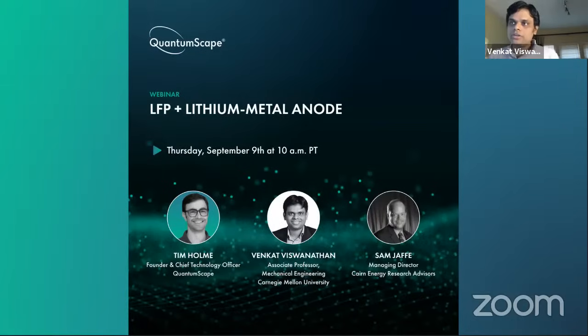One important point to note here is that lithium metal can come in two flavors. The flavor that we've discussed here is the anode-free configuration, in which the lithium metal is plated on the first cycle. The second configuration, also being pursued widely, is to have a preformed lithium foil on the current collector, copper, and use that lithium foil in a lithium metal LFP battery. What we find, in congruence with what Tim and Sam have talked about, is that pairing lithium metal with LFP brings LFP as a cathode much closer to the layered oxide. I think that's widely clear.